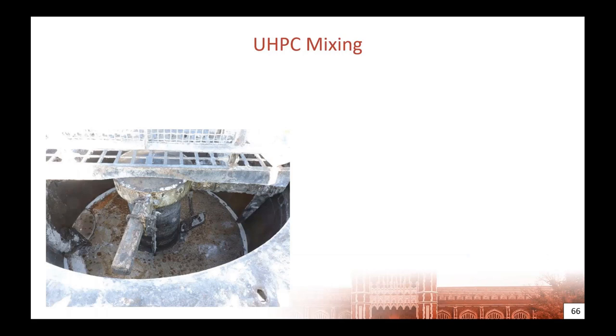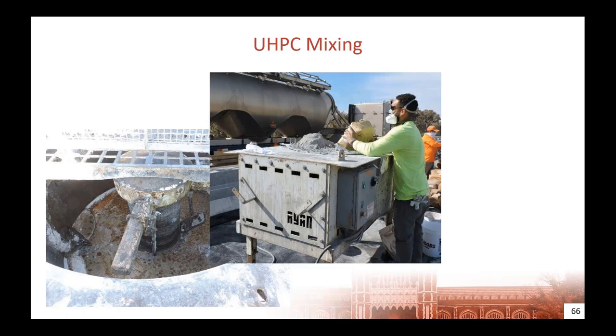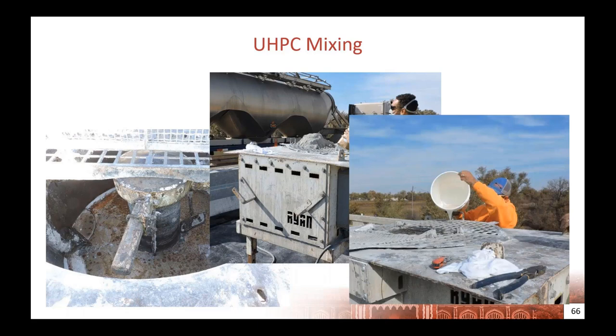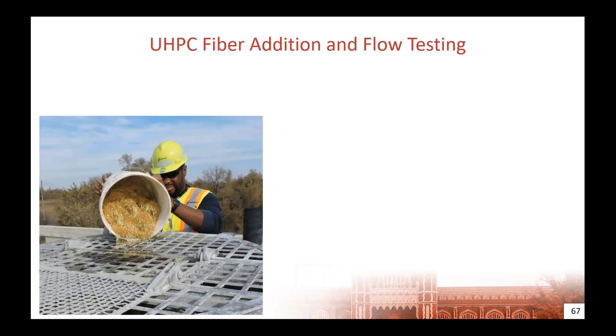The UHPC manufacturer actually provided mixers because UHPC is unique in the sense that it needs high shear mixing to actually break it apart and form the actual flowable material. So it provided horizontal and vertical shaft high shear mixers, very similar to what you would mix a mortar in. And then the dry bags were busted into the top of the mixer. After the dry material was added, the liquid material was added slowly as the mixer was run. And then it was allowed to mix for probably about 15 minutes, until it reached a point we call breakover, where it goes from a powder to a liquid.